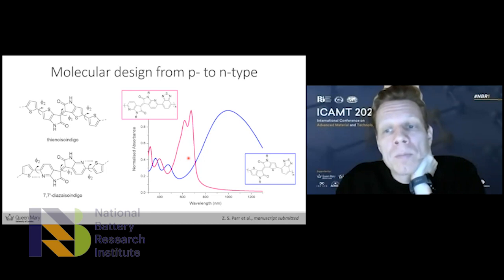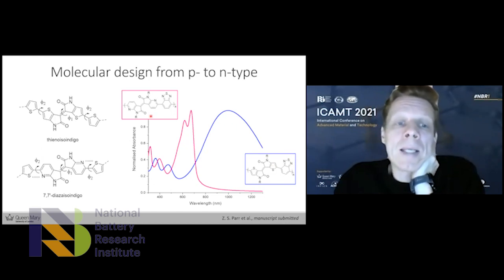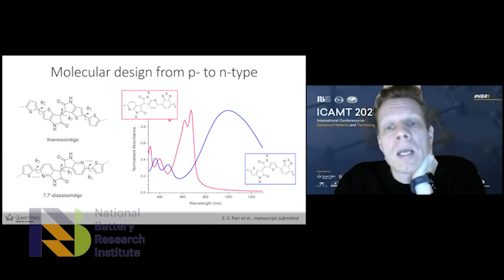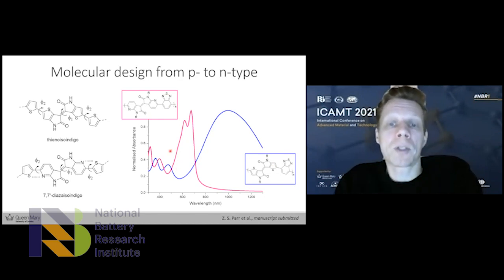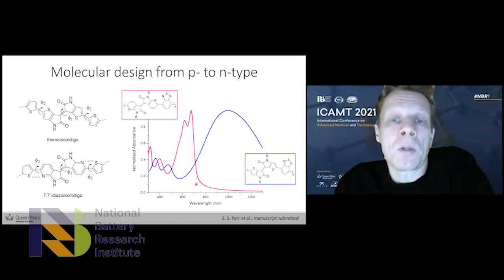The thieno isoindigo, here polymerized with an electron-deficient benzothiadiazole, has a very narrow optical band gap. You can see the absorption is out in the near IR, whereas the aza isoindigo, again polymerized with the same benzothiadiazole, absorbs around 600 to 700 nanometers, so in the visible part of the spectrum, and has a much wider optical band gap. So that's summarized here.